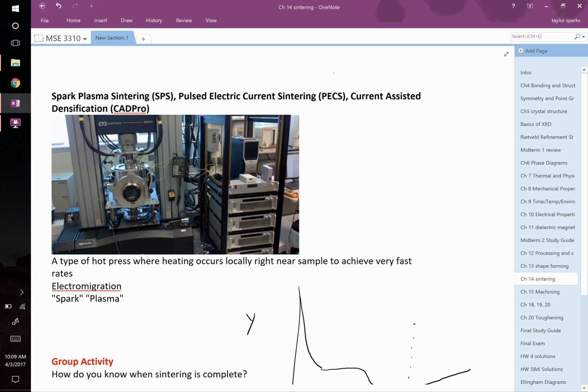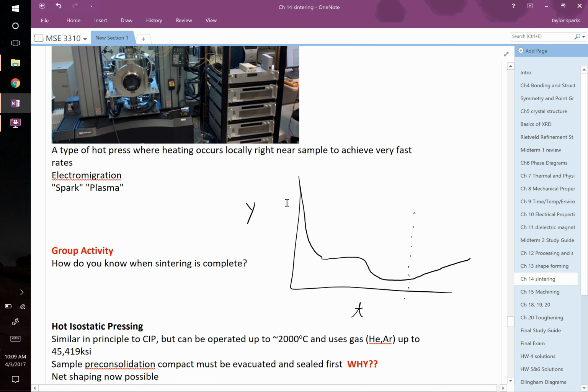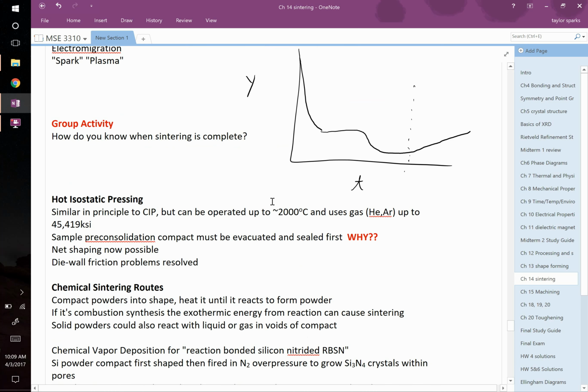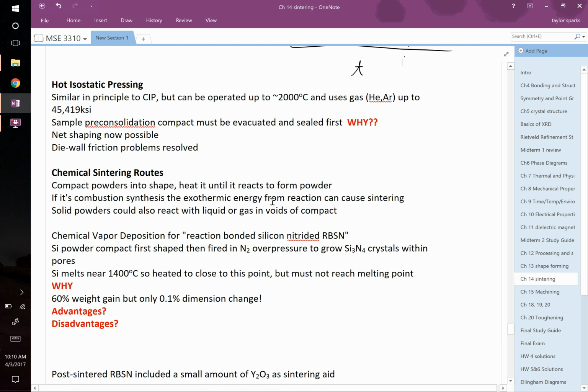There might be other systems out there that are more robust. That's the ones I've used, where you let it cool down on its own until it's around 200. And the outside actually cools off really quickly because it's only being affected by radiative heating. The one that takes a while to cool down is your sample, the die itself, and that takes an hour, maybe 2 hours. And that's the slowest part of the process. But monitoring the crosshead is something people don't realize that a lot in the industry. A lot of people just throw it in, they follow a recipe, they're not actually watching, and then they over-sinter it. They cook it for longer than it needs to, and grains grow larger than they want them to in many instances.